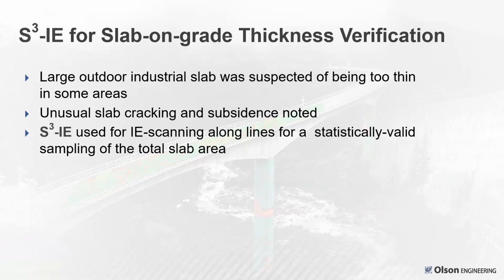It was placed, and over the course of several years after placement, they were noting issues with some localized subsidence, some localized cracking damage, not everywhere in the slab, but just certain areas as they were driving trucks over it. So the suspicion was that maybe this slab was not very even. Maybe there was issues with how thick it was.